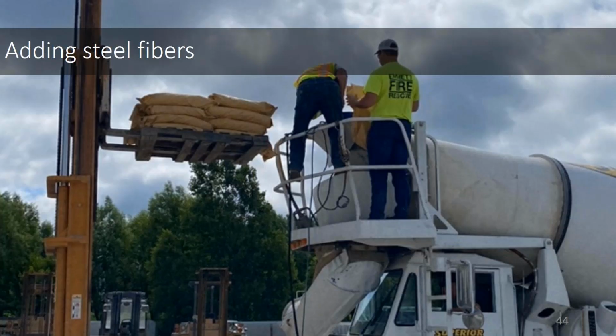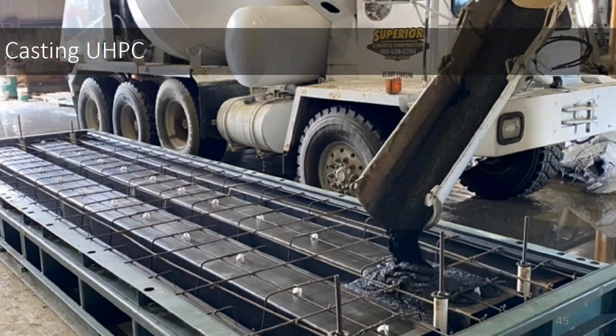The steel fibers are one of the things that takes a little bit longer to do. Once we know we have the right slump, we look at the truck, and most trucks have a flow meter and a pressure meter. We'll watch that, and once it's the right fluidity, we start adding the fibers. As you can see in the truck, there's a small blue barrel on top of the chute with a little vibrator on it. These steel fibers want to lock together, so if you dump the bags in, the vibrator shakes that little screen. It helps the steel fibers separate and go out throughout the truck.